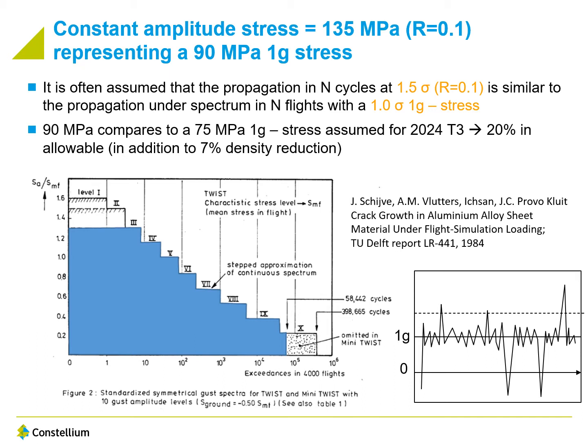It is also consistent with what you see on the bottom left, the typical TWIST spectrum. You see that, in fact, the 1.5 is also a factor that represents the maximum stress in a flight for most of the flights. In the paper, we are going to further validate this assumption based on the literature, but it's a common assumption.